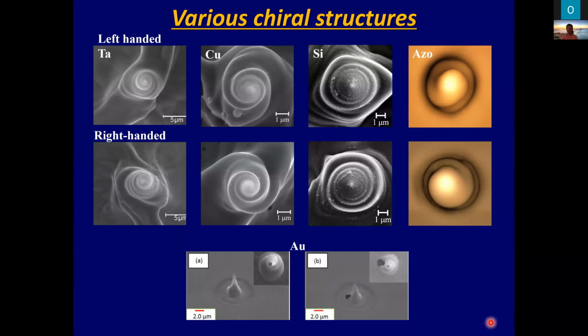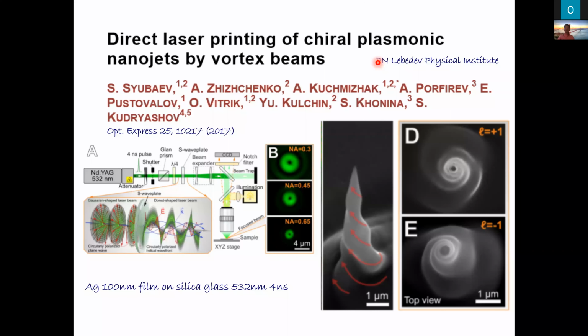This must be a quite unique material processing technique. In fact, recently a Russian group demonstrated a chiral plasmonic nanojet by illumination of a vortex beam onto a silver thin film. This demonstration is quite beautiful. They can create such a twisted needle on the surface of the silver thin film. The paper was published in Optics Express.